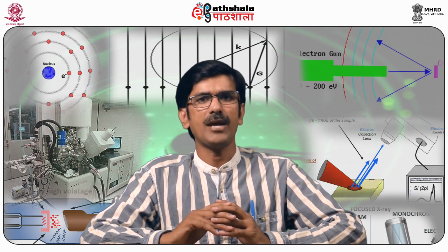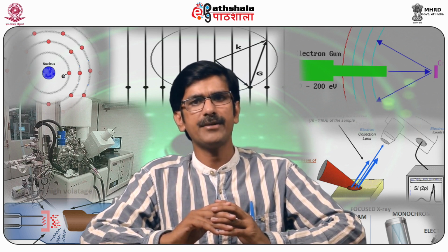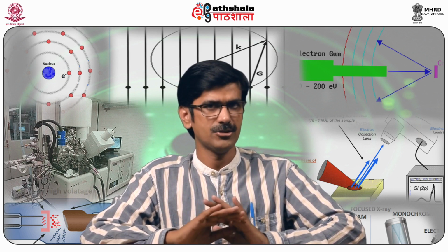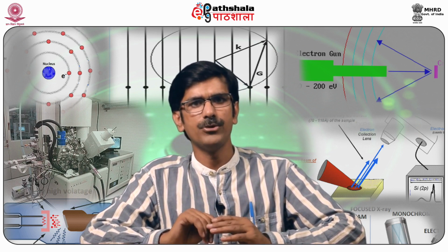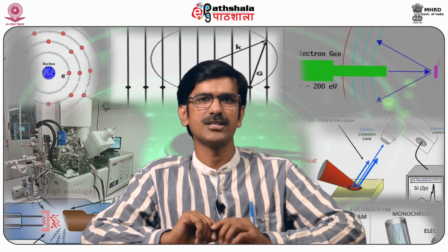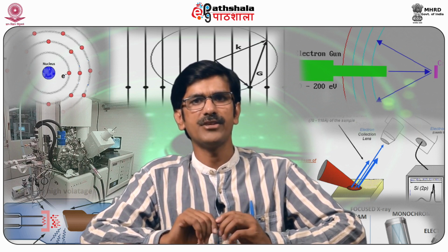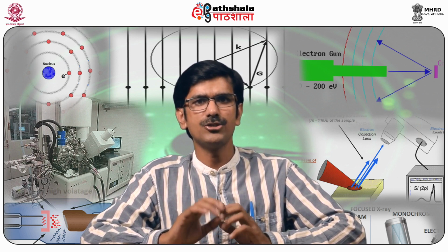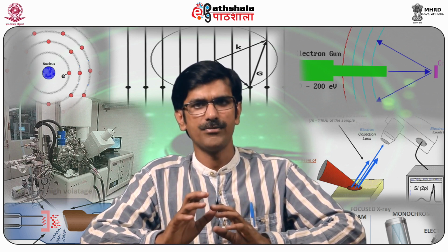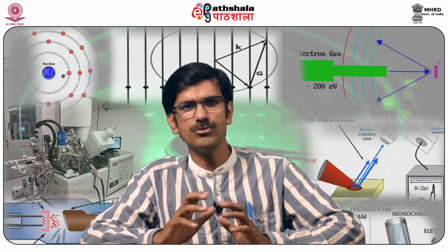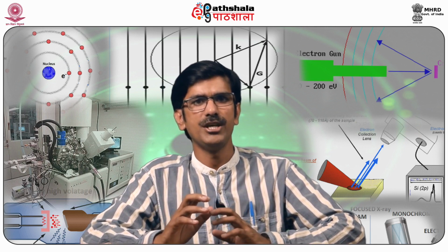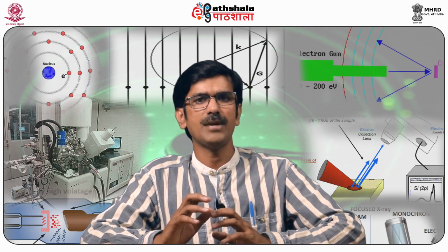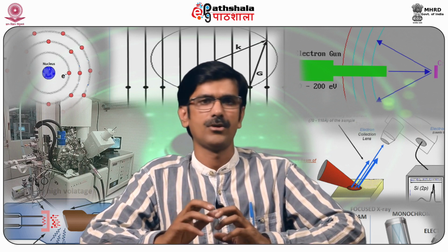If the isotherm is of type 1 or type 3, the BET method is not recommended. Not at all recommended. On the other hand, if the isotherm is of type 2 or type 4, the BET is suggestive provided that the value of C is neither too low nor too high. If the value of C is found to be high, then the presence of microporosity is assumed even if the isotherm is type 2 or type 4.